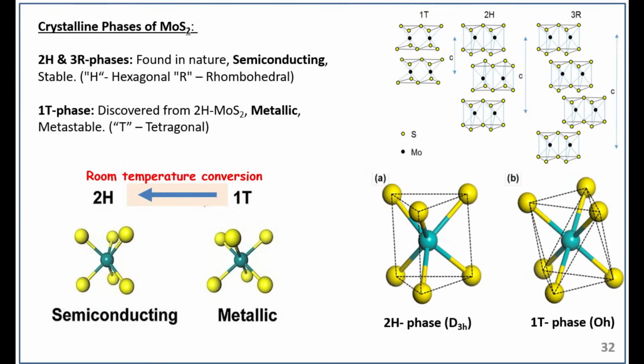So there are crystal phases, two phases. There are 2H and 3R found in nature, semiconducting. The stable H means hexagonal and R means rhombohedral. The 1T phase is discovered from 2H, it's a metallic phase. It's called tetragonal, right? Normally the 1T at room temperature converts back to 2H because the metallic phase immediately converts to semiconducting. So at around 30 degrees, it will automatically undergo phase conversion.